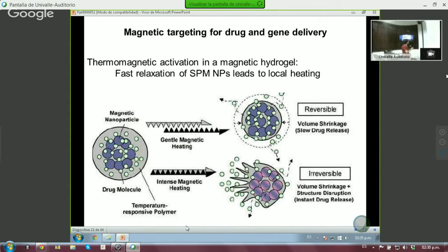One can do it with a very gentle magnetic heating. So you do it gently, and what happens is you go through a volume shrinkage, a slow drug release, and the process is reversible. You do it in a gentle way and wait for it. The second alternative is to use an intense magnetic heating. You apply everything one time, and then let's see what happens. In this way, you cannot go back and repeat the process. You do it in one shot and deliver everything at the same time. It is called an irreversible procedure because you cannot go back.